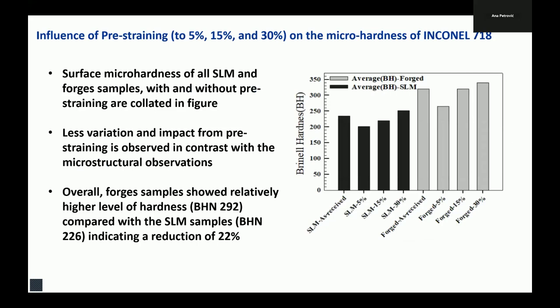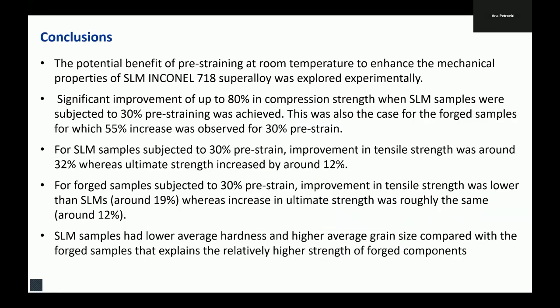If we look at the surface hardness, we can see generally forged surface hardness is higher, but not very significantly. And these are the records of the Brinell hardness numbers that you can see. There is not significant impact from the pre-straining on the level of the hardness that we get for both the SLMs and for the forged ones. So this is an observation that we can put into a number of conclusions.